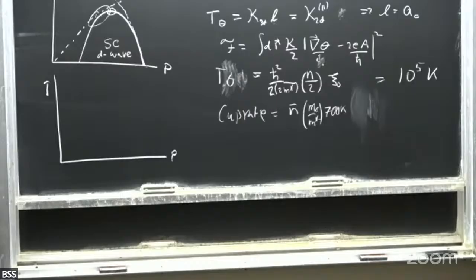Yes, good question. So they're 2D-like in the sense that they have a big resistance anisotropy. The electrons move much more easily in 2 dimensions than in 3 dimensions. And so for many properties, certainly if I'm thinking about the mechanism of superconductivity, I'm perfectly happy to think about 2D models. But when you study critical phenomena, the rules of the game are a little bit different. If I have a layered system with weak interplane coupling, it very, very rapidly crosses over to 3D critical behavior. So even with enormous anisotropy, you would expect to see 3D critical behavior over most ranges.